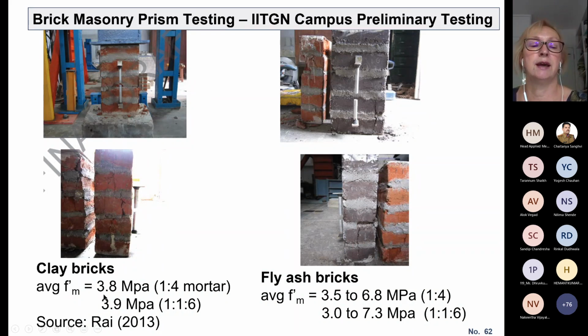The values they were getting using the local bricks from Gujarat were 3.8 megapascals for 1/4 mortar, one cement, 4 sand, and 3.9. So a very small difference for the other mortar, which is weaker in reality: 1 cement, 1 lime, and 6 sand. So 3.8 to 3.9.